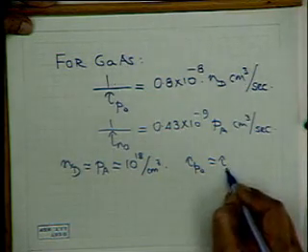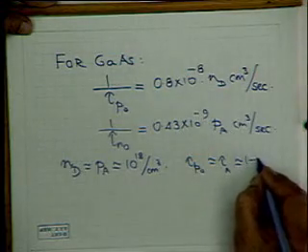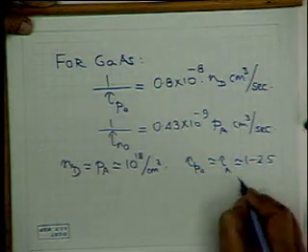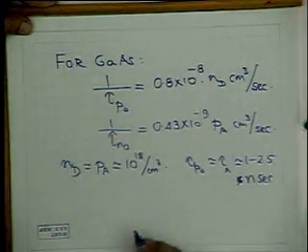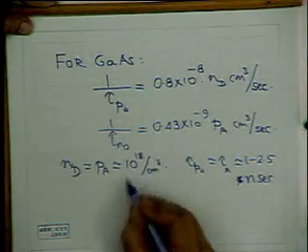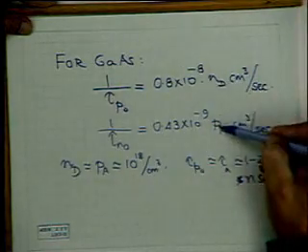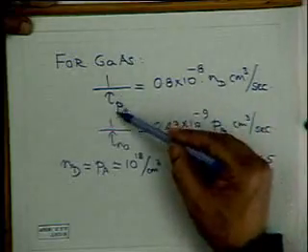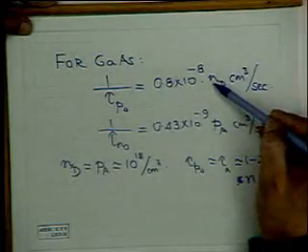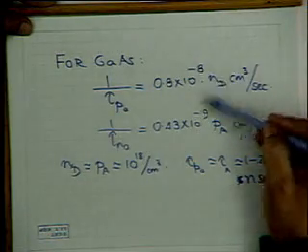These are of the order of, say, 1 to 2.5 nanoseconds. If ND and PA are smaller, then obviously the rates 1 by tau P are even smaller, and lifetimes will therefore be larger, right?